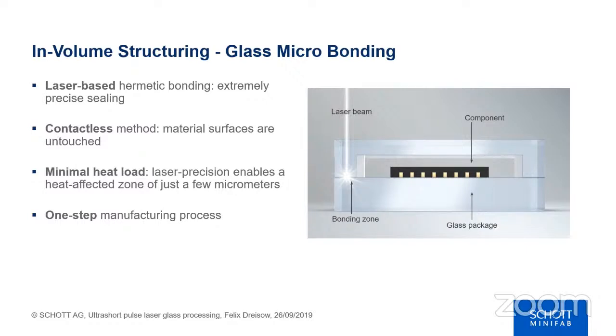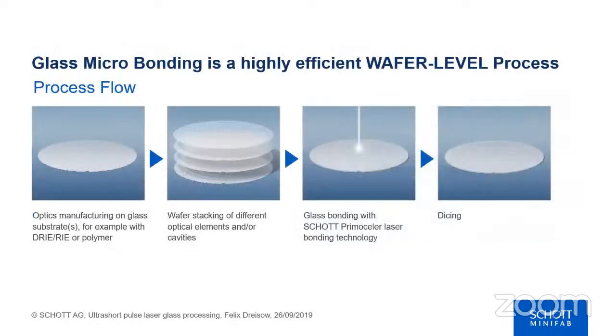You still hear me? Yes, we can still hear you. Okay. You focus the laser beam into the interface and weld the glass, but your glass component stays cold, and you weld it in a very localized position, so you protect your components or the delicate parts of your later device. And how does it work? You just have several wafers, stack them together, weld them with our so-called Primoceler laser technology, and finally you dice it to your desired size.